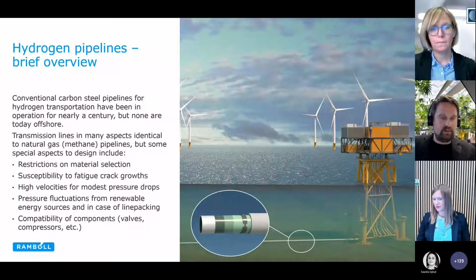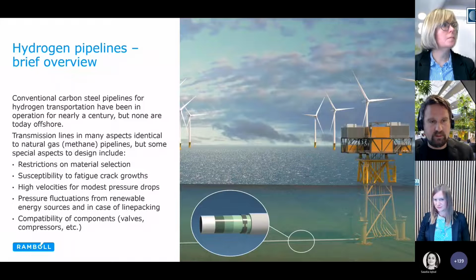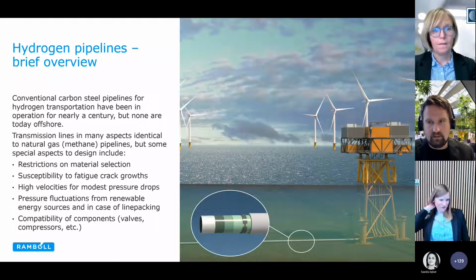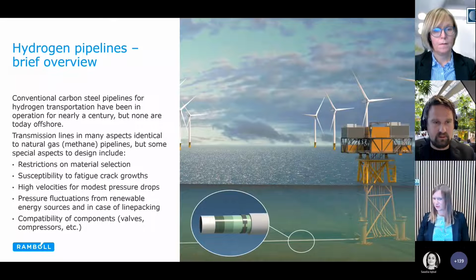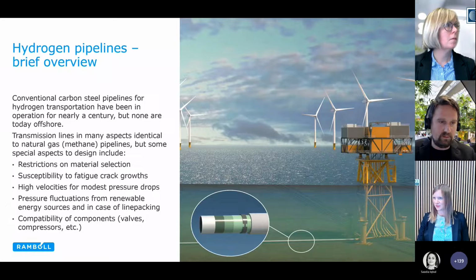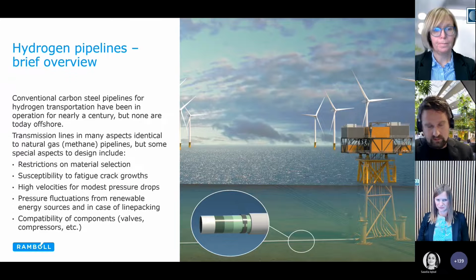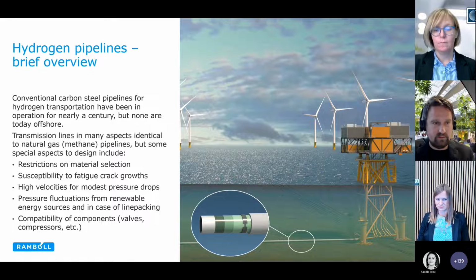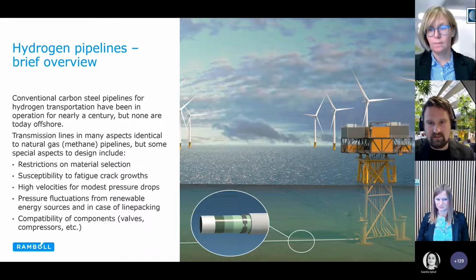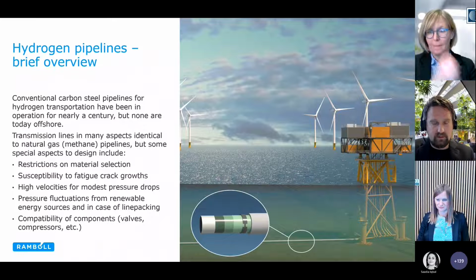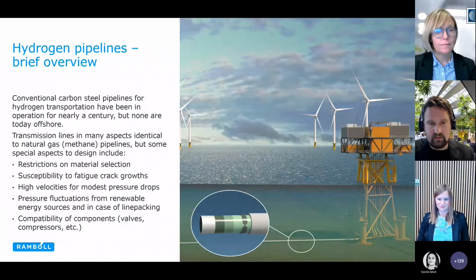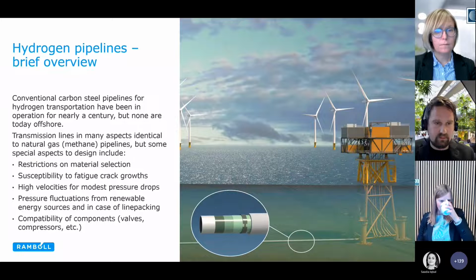We see a lot of similarities between the natural gas or methane pipelines and the hydrogen pipelines, but there are some key areas where there's difference. Main point being there are restrictions on material selection, either considered unacceptable, or that you need to add additional safety factors. There is a susceptibility of fatigue crack growth. Well, if the crack starts and if the hydrogen is attacking it, then we see a more rapid fatigue crack growth compared to the natural gas.